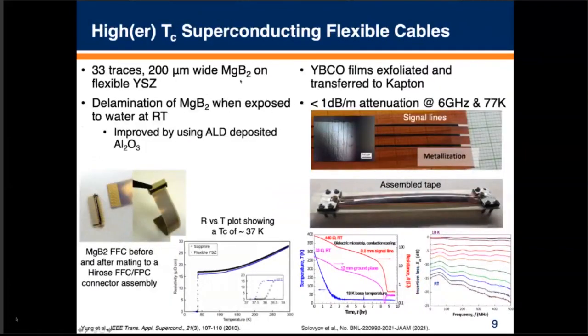An obvious question that comes up is what happens if you move to higher temperature superconductors? And so here's a couple of results. This was for magnesium diboride that was put onto flexible YSZ, which is a ceramic. And you can see they showed some nice transition temperatures of around 37 Kelvin for these devices. And then in terms of YBCO, there's an exfoliation process to transfer that to Kapton, and you can see here they've got their transition temperatures as well as insertion loss associated with that as you go from room temperature down to about 18 Kelvin. You see a nice drop off of that. And a neat looking structure here with the signal lines transferred to the Kapton as well.